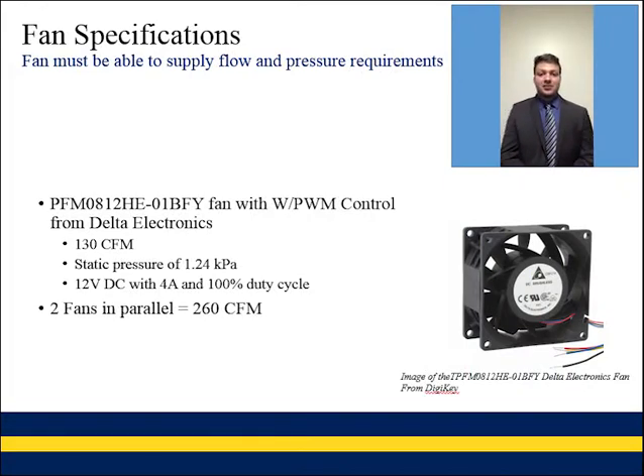Once we were able to obtain our results and the specifications that we needed from a fan, we were able to choose a fan. We ended up going with a fan from Delta Electronics that we purchased through DigiKey. The fan is able to supply 130 CFM, which isn't enough, but if we bought two of them and put them in parallel, it would provide about 260 CFM, which was more than we needed, which would end up helping more with the cooling. The static pressure from these fans was about 1.24 kPa, or 5 inches of water, which is more than what we needed. And to power these fans, they need about 12 volts DC with 4 amps and 100% duty cycle. These will be powered through lithium-ion batteries.